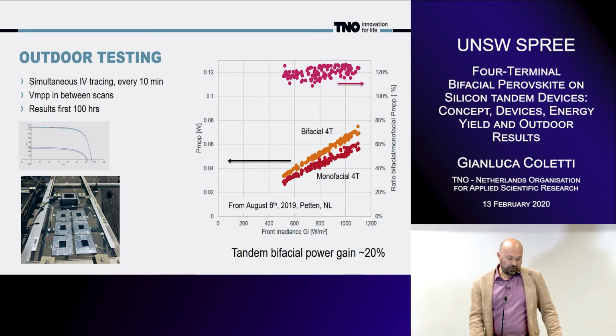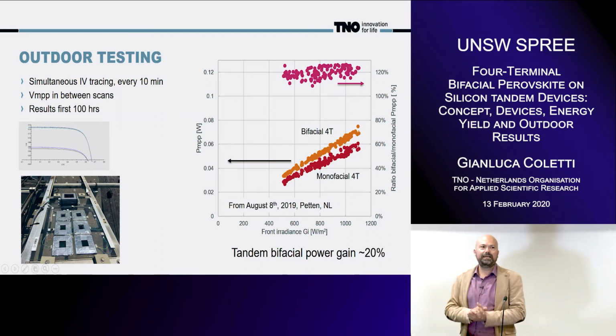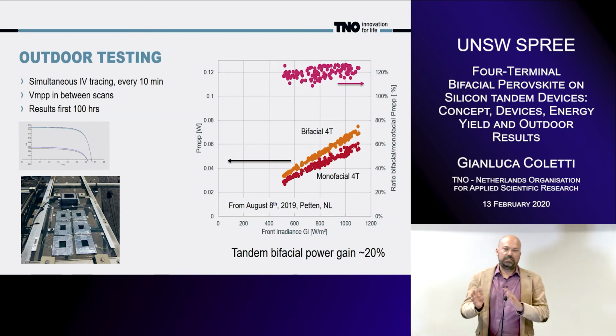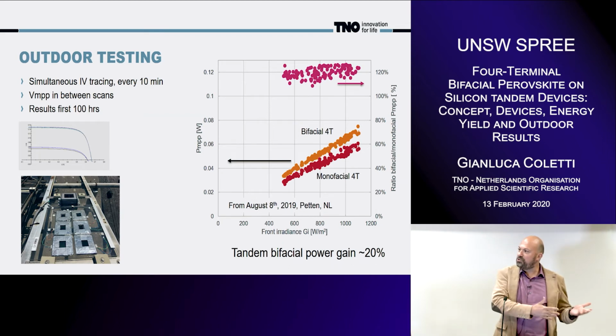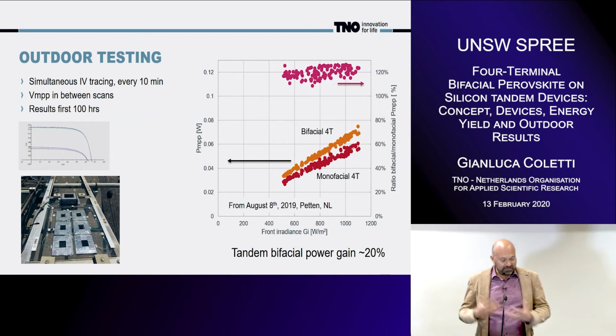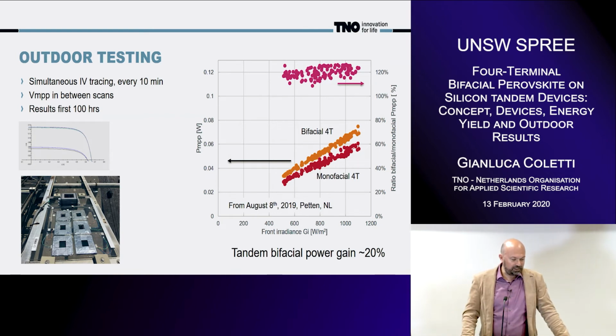And so we did. So you see here on the left side the module in the outdoor configuration. There is somehow concrete on the rear side, and the albedo of concrete changes, of course, depending on the real color, but it's between 20 and 40%. We expect this to be 30%, which is what we use in the calculation, to try to see if this result validates our model.